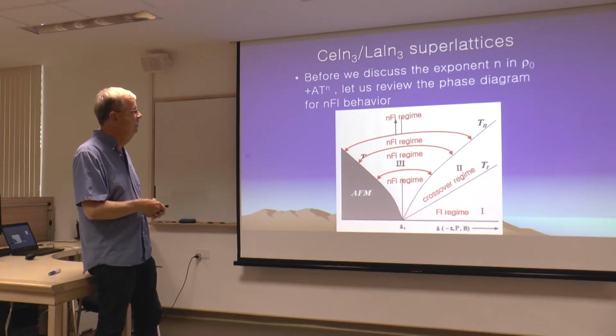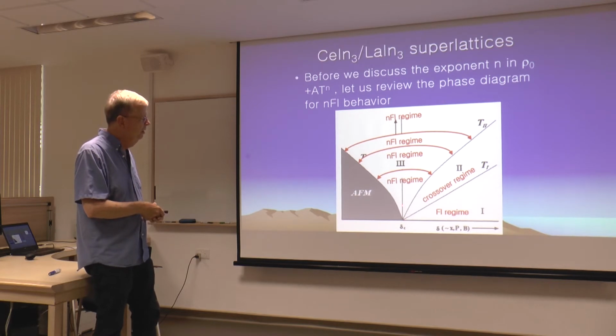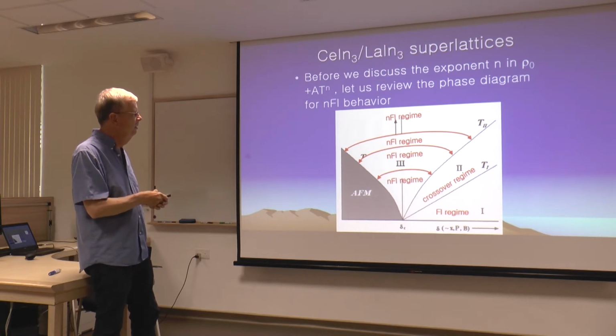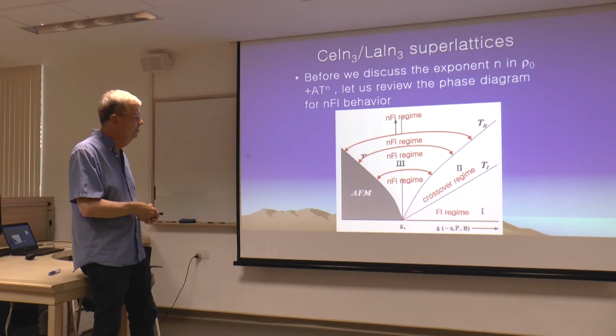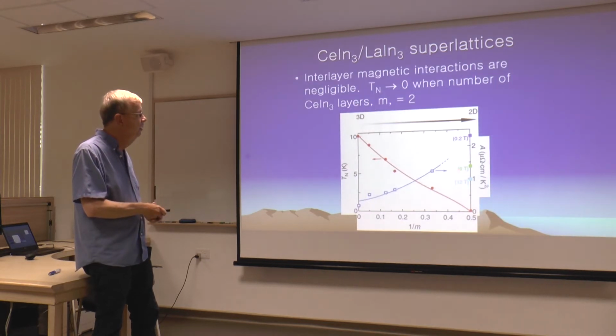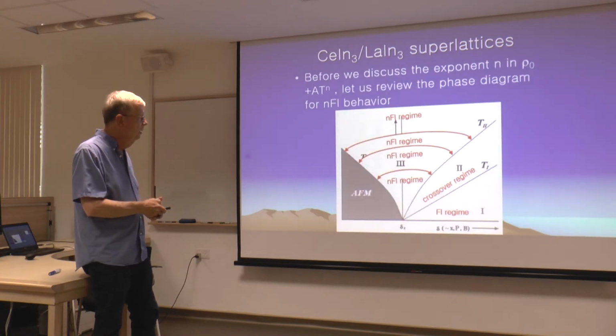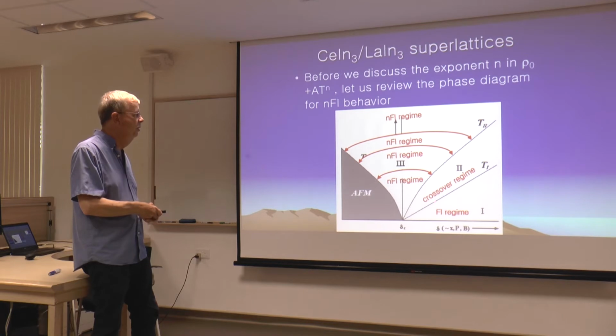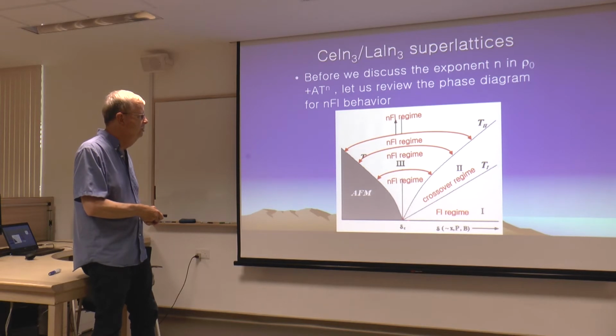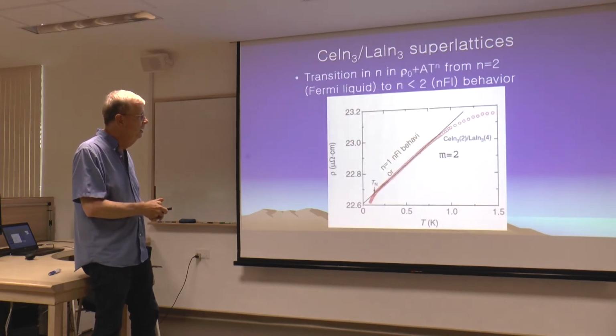If I measure the resistivity sort of directly above the tuning parameter and not too far over, I can get non-Fermi liquid behavior. Now over here, as I run the tuning parameter or a tuning parameter higher, for instance, magnetic field, if I run the magnetic field higher, for instance, I go from 0 to 0.2 Tesla, that point right there. According to this, I can get Fermi-liquid behavior. So below a particular temperature, I can get Fermi-liquid behavior as I tune the field here. So that's what I'm claiming is happening here.